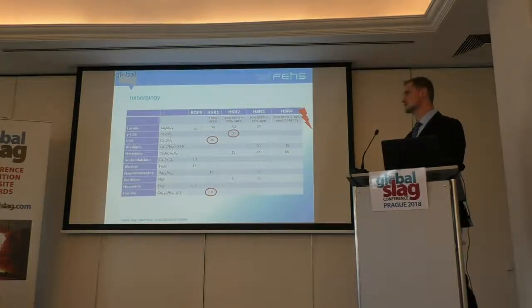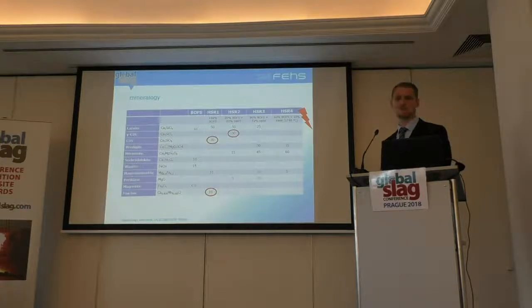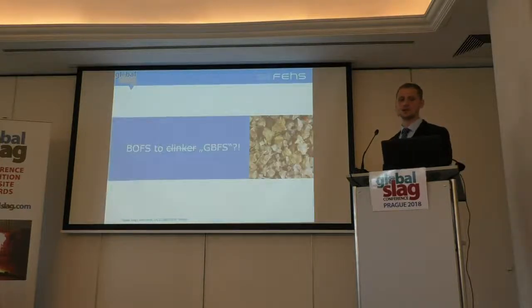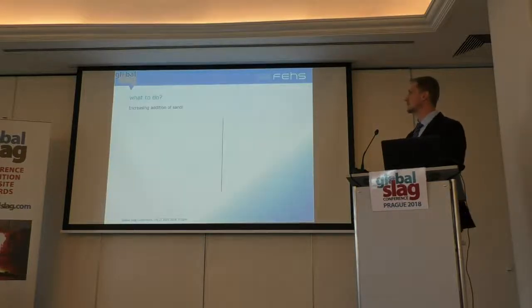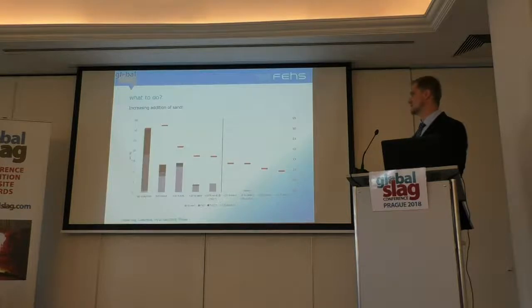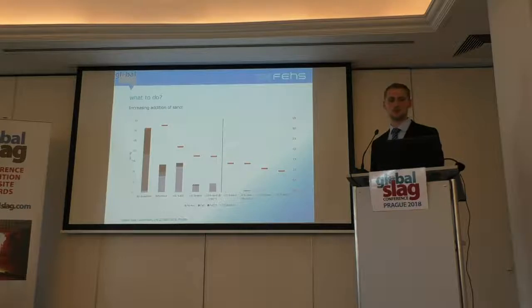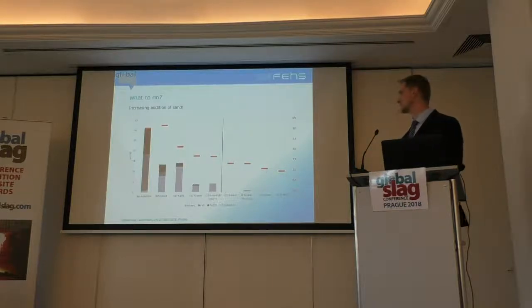So we said that's not really a way that could fit in industrial practice, so why don't we try to make a GBFS-like material from BOF slag and not a clinker-like material. So what to do? We have to increase the addition of sand. Here's a picture I showed you before, and now we added more than 10% sand. We added 15%, 20, 25. You see the basicity, sure, it decreases, and the slag was very, very reactive, very low viscosity, and we have no iron in it, so everything was reduced.